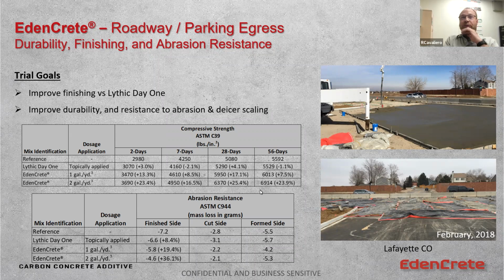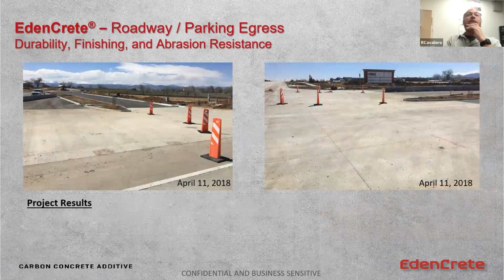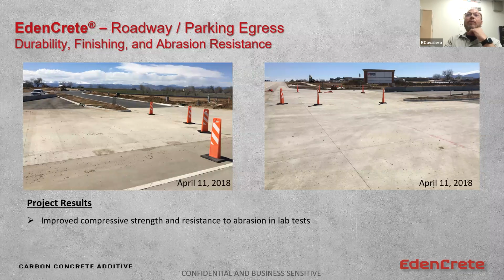When we look at abrasion resistance, which is the reason this product was used by Colorado DOT, and we look at one of these tests, the reference lost 7.2 grams after the test. The product intended to improve abrasion resistance lost 6.6. It improved 8.4%. And then when we used EdenCrete, we saw those drop and begin to get into double-digit improvements again, right? And so this is about long-term performance, resistance, being able to endure what's going on out there over time before more resources have to be put back to it.